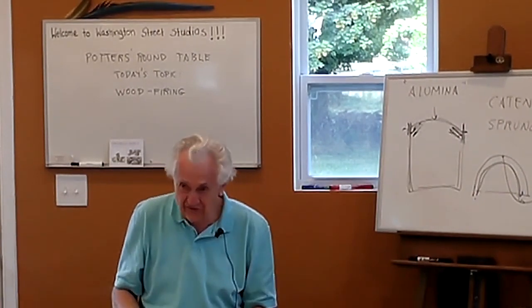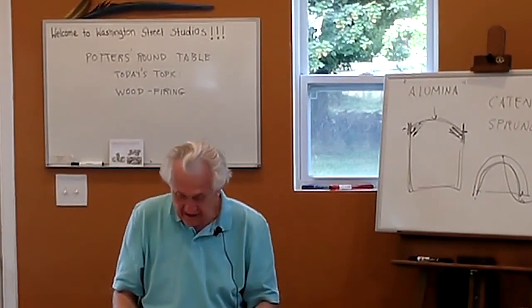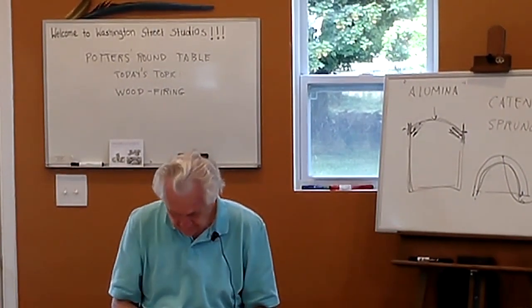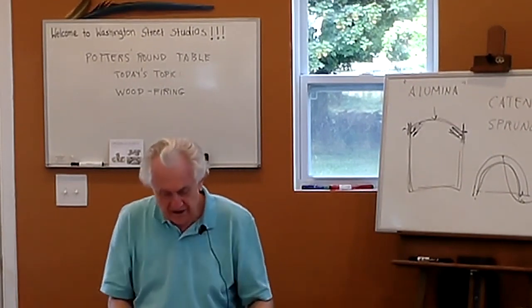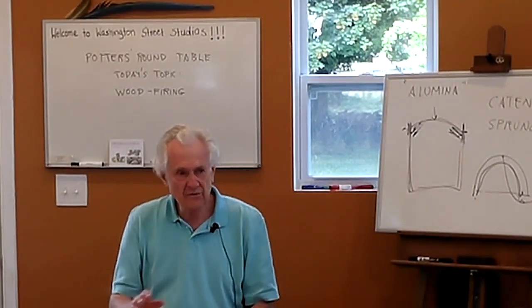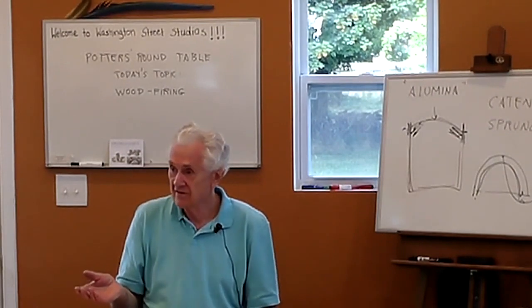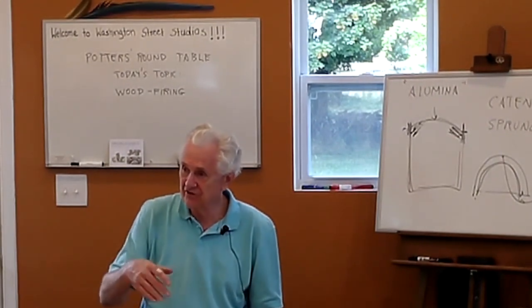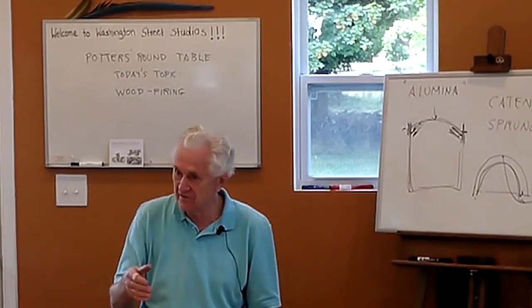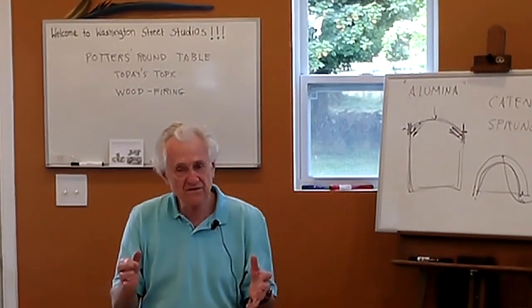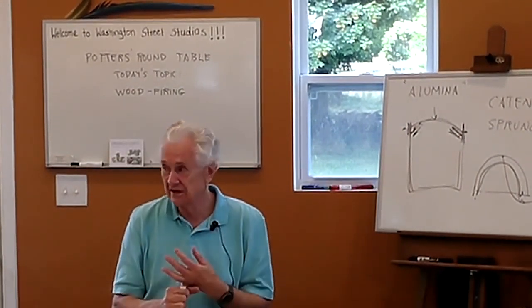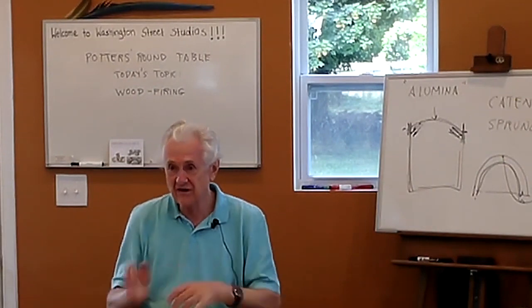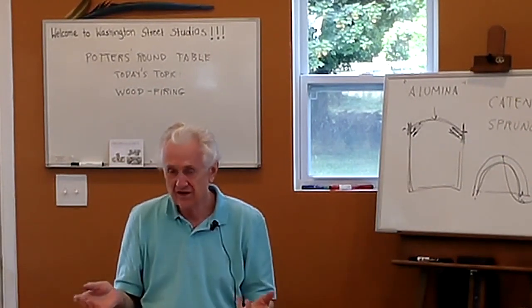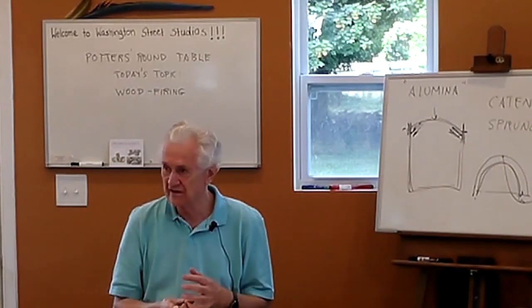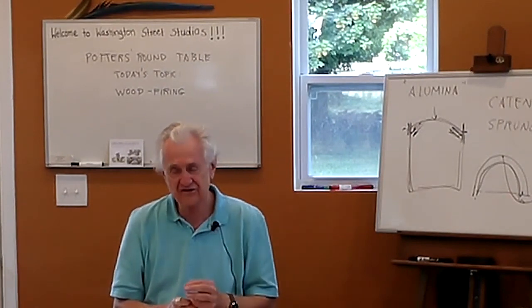So the kiln design has a big effect on my ability to heat up the kiln quickly. And then when you're actually stoking in a wood kiln typically, is everybody familiar with the term reduction? This is basically where you're burning a fuel, but you don't have enough air to completely burn the fuel. And the only reason why you fire in reduction, really, is color. That's the only reason to fire in reduction, because everything else is the same, essentially. So you're looking for different color changes in the clay and different glazes and ash effects and flashing and so